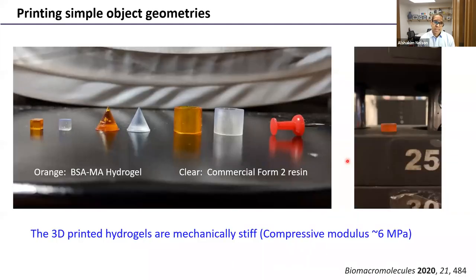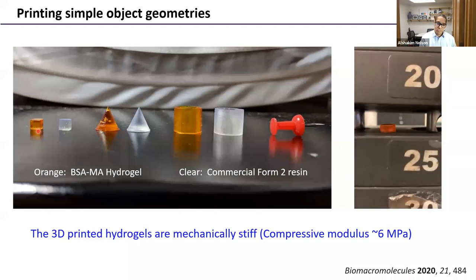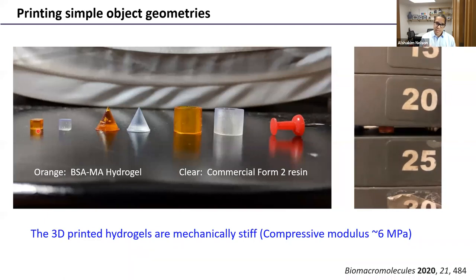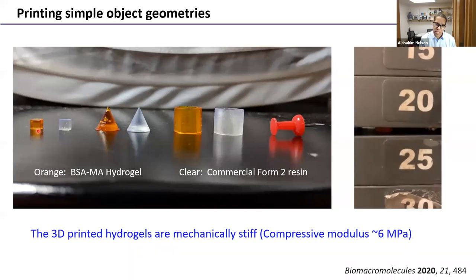And just to give you a sense of how well we can print these materials, these are side-by-side comparisons. The clear material is the commercially available resin. The orange ones that are next to them are our printed hydrogels, right? So I should mention again, because we formulated these in water, when they're photocured, these are hydrogels, but these hydrogels are actually mechanically very stiff. And I told my student to put some weights on this hydrogel so we can give people a sense of how stiff these hydrogels are.